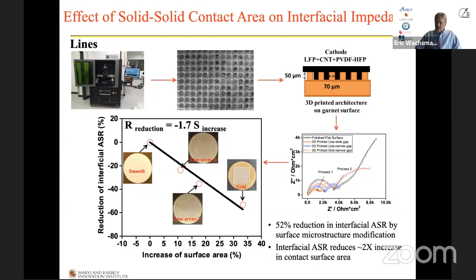So the figure to the upper left is just a smooth disc of the garnet. And you can see as we increase the surface area of this 3D printed garnet on top of it, going to lines and then ultimately to grids, that the area specific resistance drops linearly with the increase in surface area. So as you increase surface area, resistance decreases, and there's a direct linear relation to it. And that's again why you want to make these types of structures, because you want to reduce the resistance of the cell